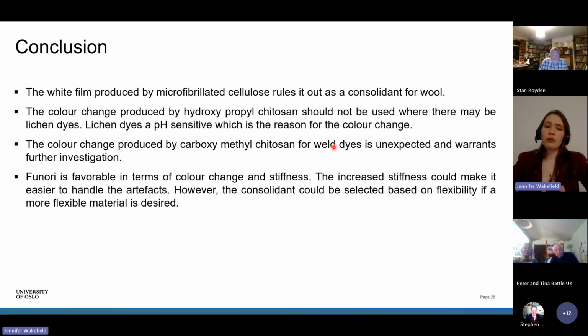So in conclusion, the microfibrillated cellulose produced a white film, so it rules it out for a consolidant for wool. Hydroxypropyl chitosan produced a color change with the lichen dyes, which again can be a problem. So if there's any sort of suspicion of pH sensitive dyes, it can't be used. Same with the carboxymethyl chitosan, where there's presence of weld, again, this warrants a bit of further investigation, but caution should be taken if choosing to use this as a consolidant.